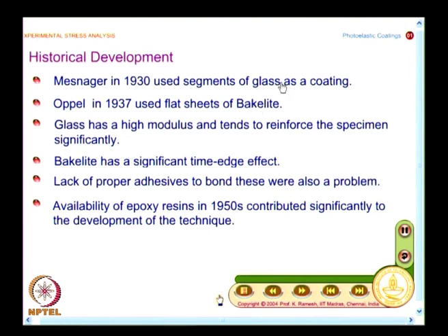And after glass, what did they try? Oppel in 1937 used flat sheets of bakelite. So, when we graduate from transmission photoelasticity to photoelastic coating, initially people concentrated only on flat surfaces. So, they initially used glass, which was found to reinforce the specimen significantly. The problem with bakelite was that it has a significant time edge effect. And we have already seen in transmission photoelasticity that because of time edge effect, spurious fringes are formed. So, you do not want spurious fringes. So, bakelite was also not a suitable material when you want to go in for photoelastic coatings.